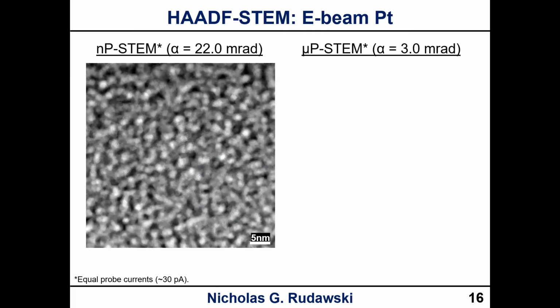All right, so now let's look at some actual results here. If we look at HAADF-STEM of just platinum deposited via e-beam, that you're making for lamella prep, here's nanoprobe STEM. Our convergence semi-angle is 22 mrad, and it's a very nice image of platinum grains. You can see atomic detail in there very clearly, just as we would expect.